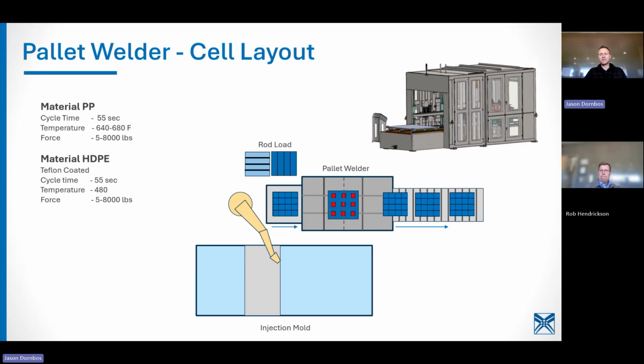Mike asked, what's the most common puck material for polypropylene? Both of these would typically use a steel puck or plate, depending on the configuration. So you're using steel for the actual heated tooling, and then for the coating, you can go with either Teflon based, though you'd have to limit the temperature because Teflon starts to break down around 550, 600 degrees Fahrenheit. If you're going to weld at an elevated temperature, then we would go with more of a chromium-based coating, which is a very hard, robust coating capable of withstanding super elevated temperatures, well above the 680 degrees Fahrenheit that we typically would use.